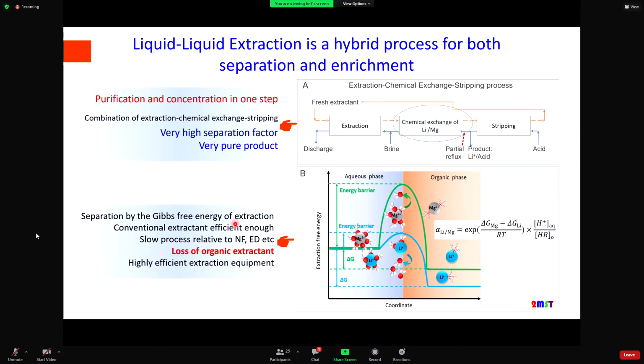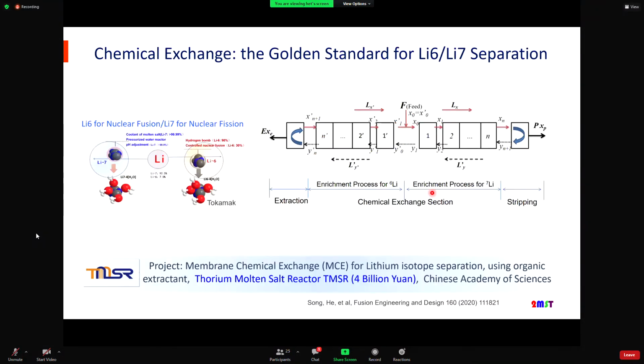This selectivity of separation is based on a formula we derived—it's based on the extraction free energy of magnesium and lithium. The problem for this liquid extraction is that because of the direct contact of the brine and the organic phase, there is a loss of organic extractant. From an environmental concern, this is not green enough. I will address this green problem of liquid extraction later using membrane extraction.